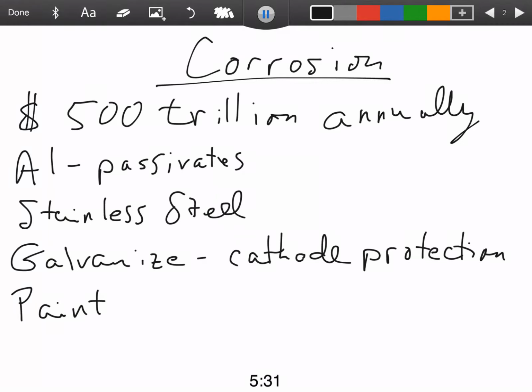Stainless steel can also be used. Stainless steel incorporates chromium, and typically what happens is that the chromium finds its way to the surface of that iron, and the chromium will also passivate, which means that it reacts with the oxygen in the atmosphere, but then it forms that nice thin coating of chromium oxide, and then the oxygen cannot get underneath that coating and react with other metals that are on the interior of that.